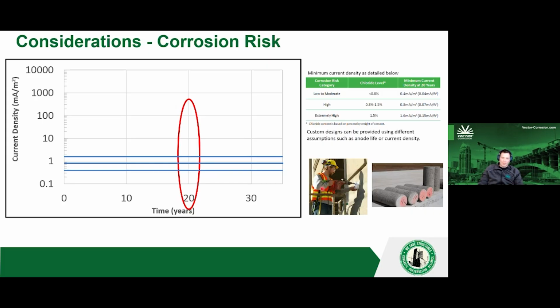Well, typically you're going to need to take a powder sample or take a core, send it to a lab, get it tested, find out what the chloride level is at your level of rebar. Because everything above isn't going to affect the rebar. But what it is at the level of rebar, that's what we care about.